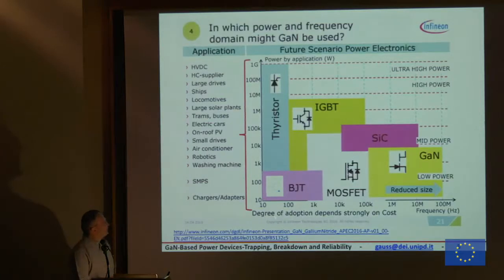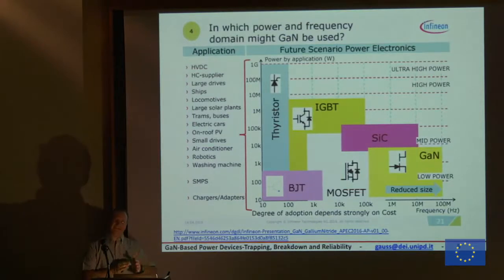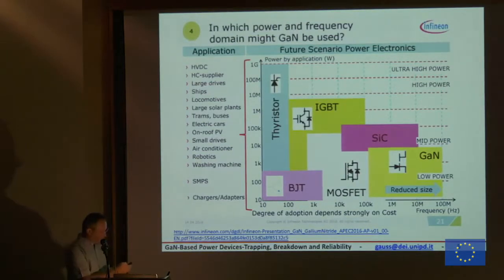But of course, this device can only operate at very low frequency. If we want to have a compact device or system, we need to go to higher frequency. Then we can have lower inductance. If a device has lower capacitance, we can make a much smaller, compact device and system. So this is why wide bandgap devices operate at relatively high power but also relatively high frequency. And GaN is a little bit better than silicon carbide because it can push to a little bit higher frequency, thanks to the better mobility of the material itself.